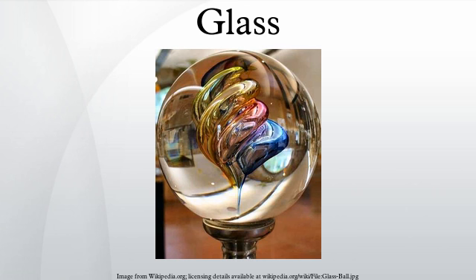Mass production of glass window panes in the early 20th century caused a similar effect. In glass factories, molten glass was poured onto a large cooling table and allowed to spread. The resulting glass is thicker at the location of the pour, located at the center of the large sheet. These sheets were cut into smaller window panes with non-uniform thickness, typically with the location of the pour centered in one of the panes for decorative effect. Modern glass intended for windows is produced as float glass and is very uniform in thickness.